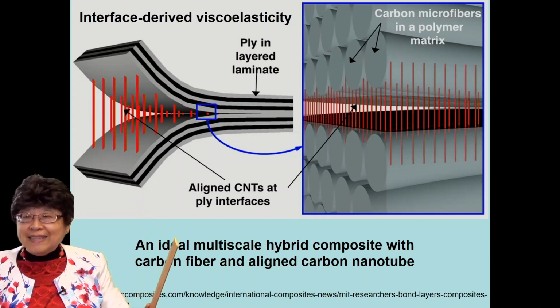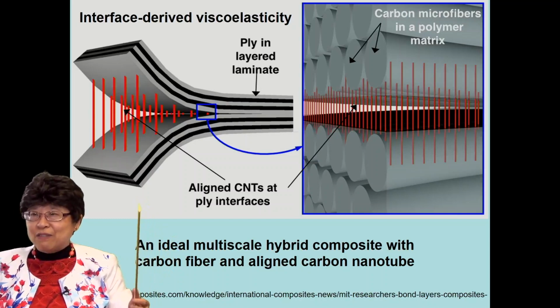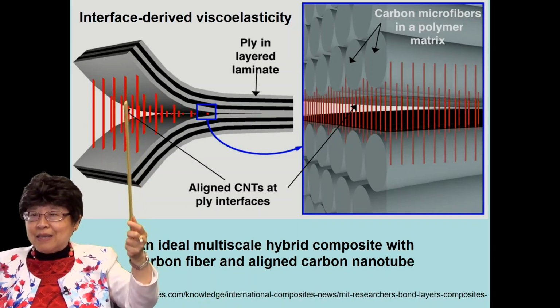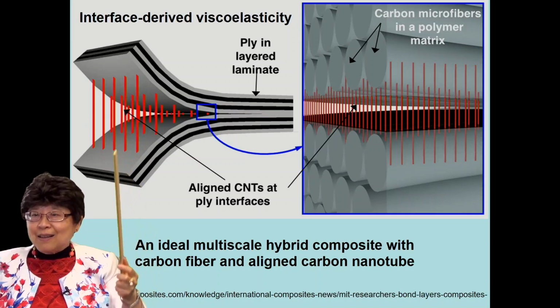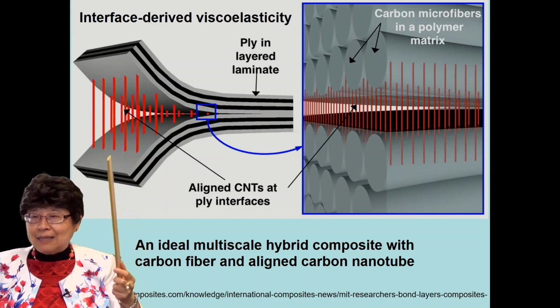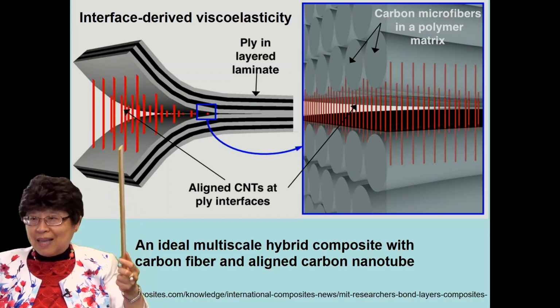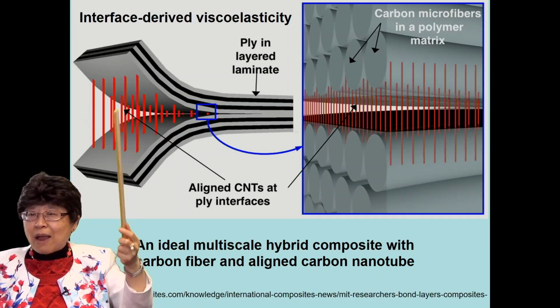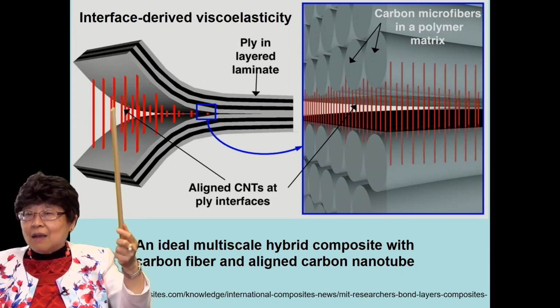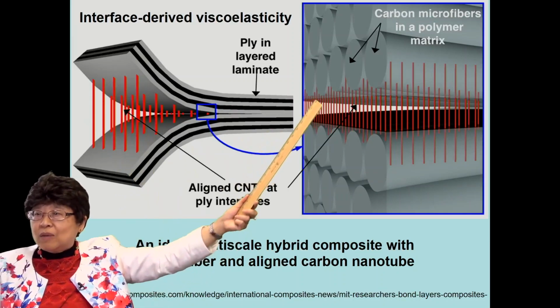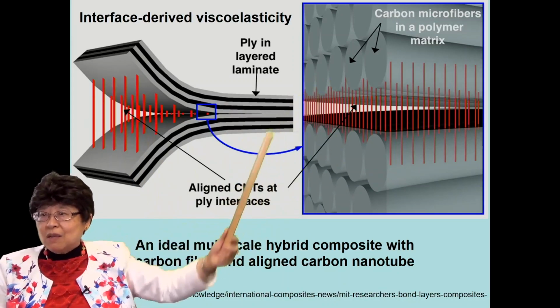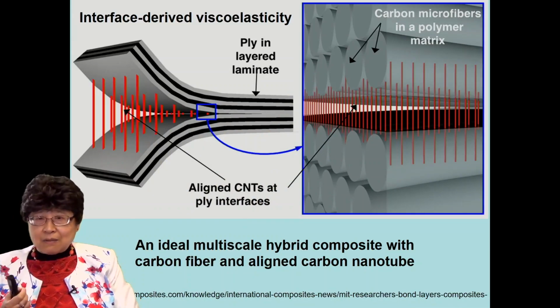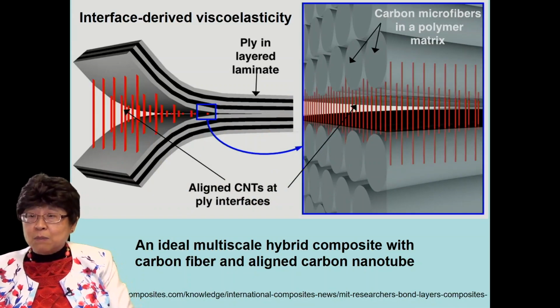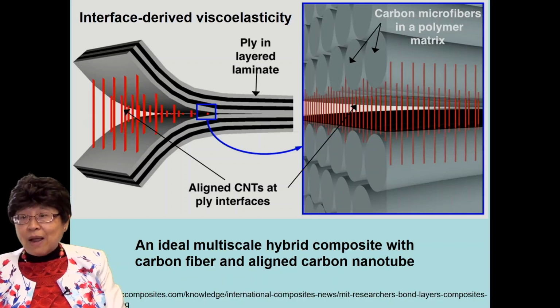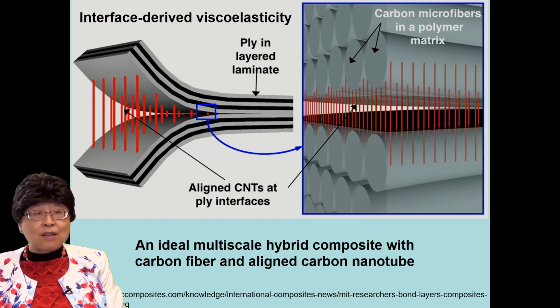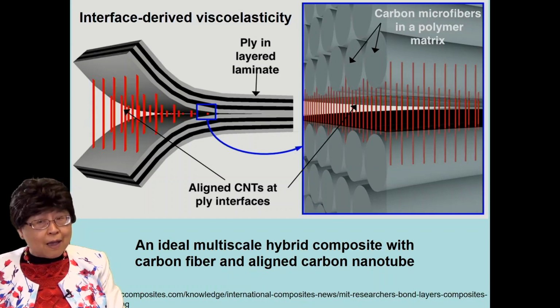This is an ideal situation of interface-derived viscoelasticity, where you have the interface being aligned, vertically aligned, carbon nanotubes in red. So as this crack opens, these nanotubes would get pulled out of the sockets, and this pull out involves friction, and so it consumes mechanical energy. This is great because carbon nanotubes are so tiny, so you have lots of interface area.